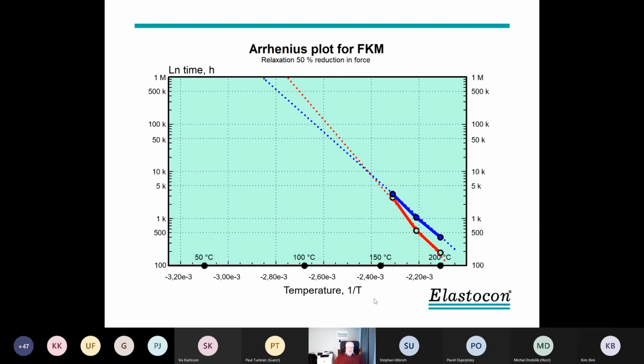Some other data on here is fluororubber. We have tested 2 different fluororubbers. You see, it's not always you get the 3 points in a good line. It happens, and most often the highest temperature is too high, and then you don't get a straight line. But the interesting thing here is to show the difference between 2 types of fluororubber. One is better above 150 Celsius, and the other is better below 150 Celsius. So they have quite different activation energy.